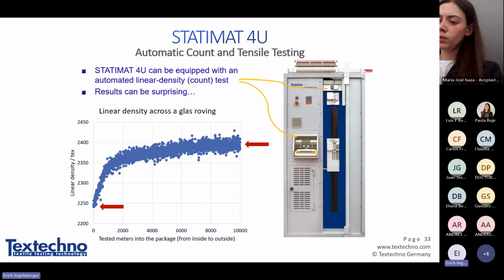In addition to the tensile testing zone, we also can, by using the so-called auto count module, measure linear density, which is the weight of a certain length of yarn. Why do I show you this instrument? Because we have found a very interesting effect, which we did not expect.